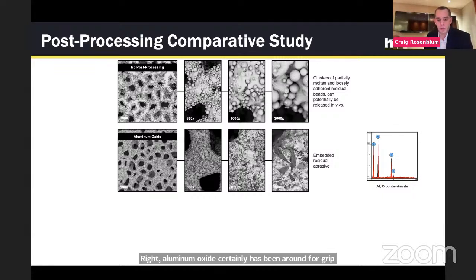For those of you that are not familiar with grit blasting, it's quite simply being able to propel this media at high pressures towards the substrate. And ultimately what happens is that the aluminum oxide effectively knocks off the residual beads. And certainly you can see that that's the case.